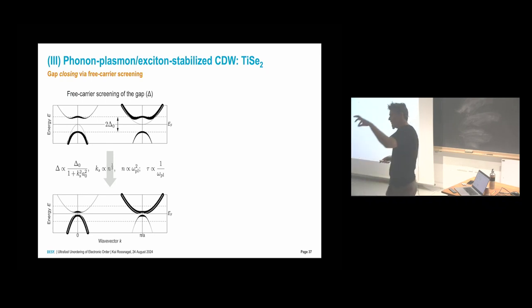It's the free carrier screening. So you create a free carrier plasmon, and it's free carriers that create the hot electrons, and they screen the interactions. Yeah, so I imagine it in this way. So here you have the gap, and here you would, let's say, have Thomas-Fermi type screening with this screening wave vector Ks. Ks is proportional to the electron density to the power 1/3, and the electron density is proportional to the plasma frequency squared. So this in a sense, yeah. And then the time scale is given by the plasma frequency.